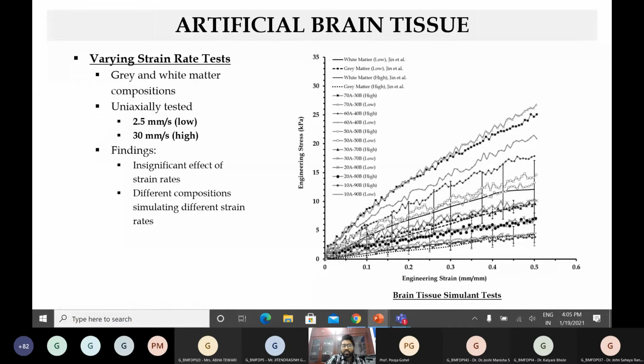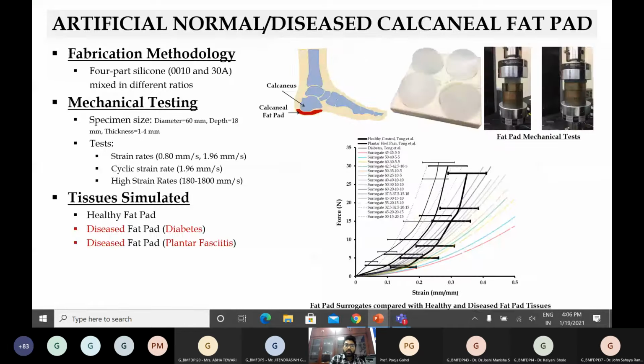So what we came out with were different compositions simulating different strain rates, meaning for the same tissue property, when it is tested at two different strain rates, we have a different composition for that. That's what we came up with, because the same composition cannot work very similarly in different strain rates for the same real tissue. OK, so this is some of our findings from the artificial brain tissue mimics.